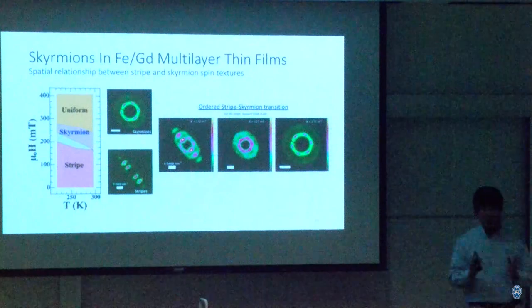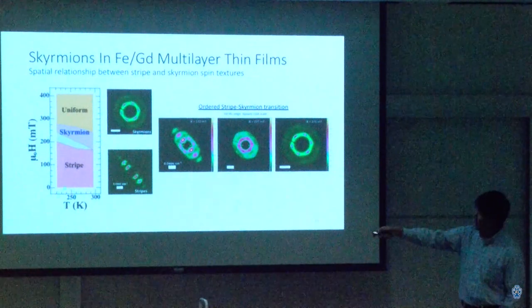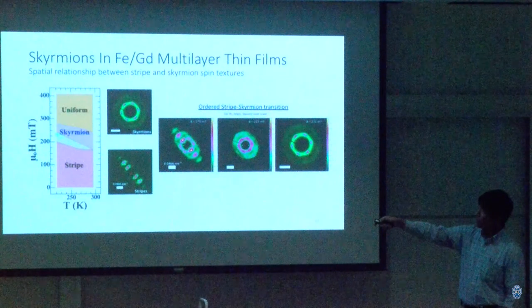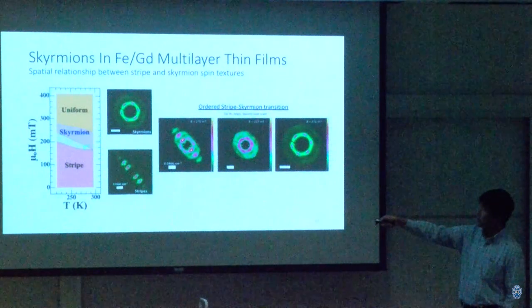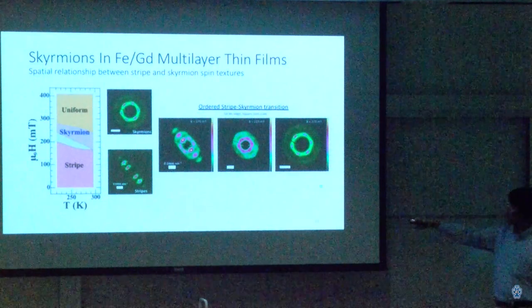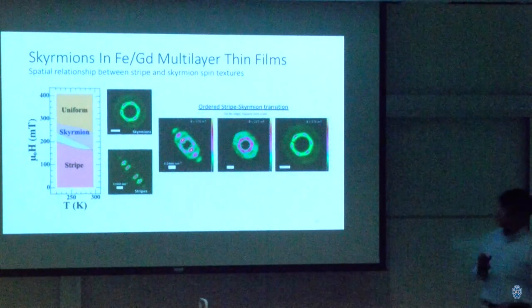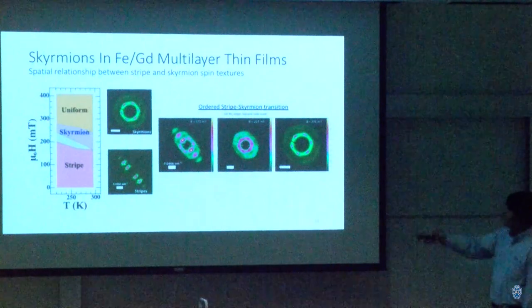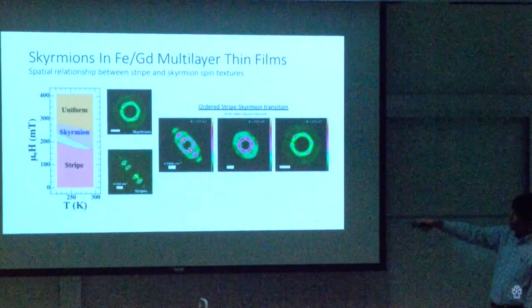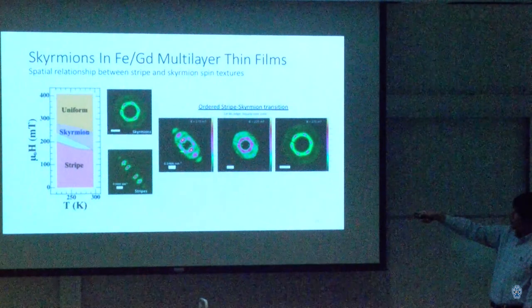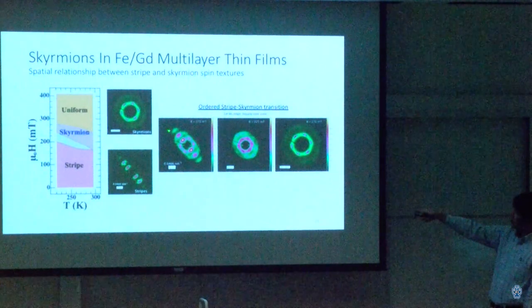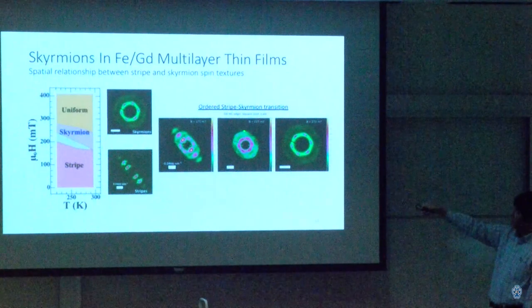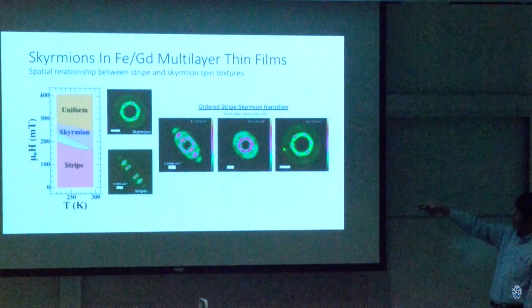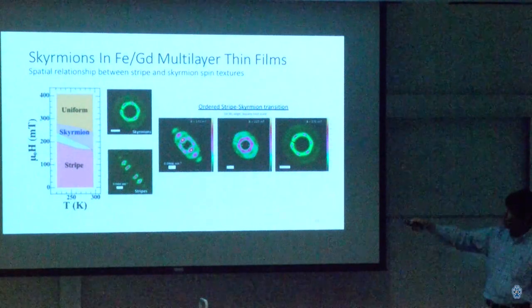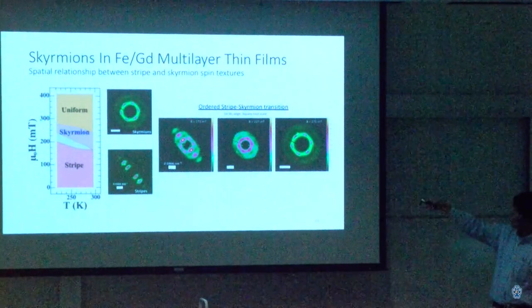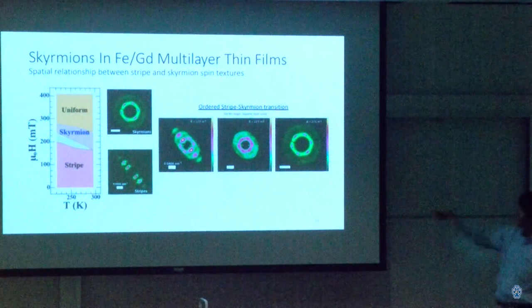But as you lower the temperature of the sample, say at 250K, a new phase appears between the stripe and skyrmion phases. And that's what's depicted here. The change of the diffraction pattern as you go from a low to high magnetic field. In this case, you can see a transition from a stripe. You now have peaks off of the main axis of the stripe pattern. As you continue increasing the magnetic field, it becomes more of a six-fold pattern. And just before the state collapses at the extreme limit of the skyrmion phase, you can see it has a very nice six-fold pattern associated with that.